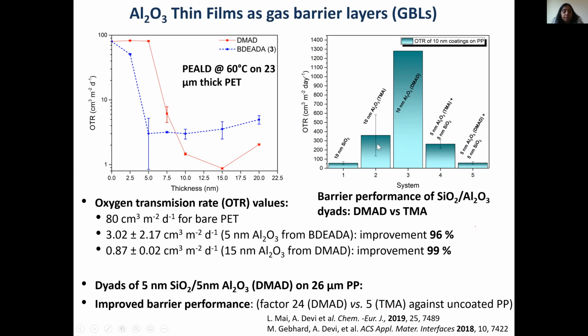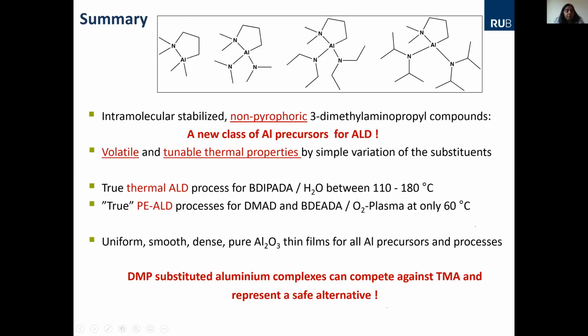So then we tried, let's see whether we can make only aluminum oxide. The OTR was not optimal, like in the case of SiO2. Then we also had some different thicknesses and also combinations, you see. Finally we found that 5 nanometer aluminum oxide and 5 nanometer silicon oxide was the optimal combination to get a very good OTR performance. So the bottom line is that the precursors have a very important influence, and the film thickness has a second influence, and one can optimize this, okay? So this is one example of the barrier performance.